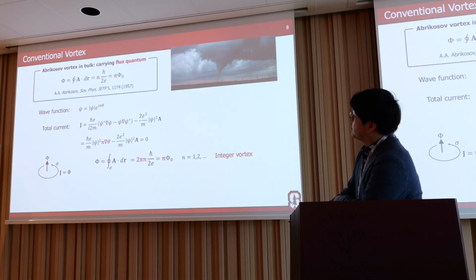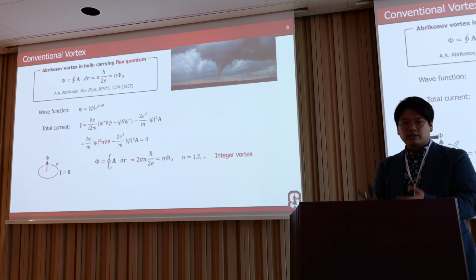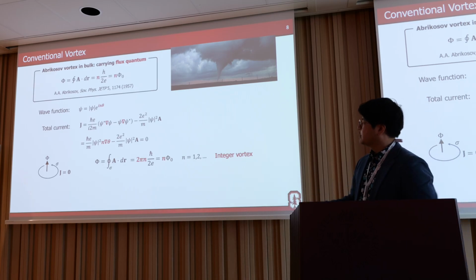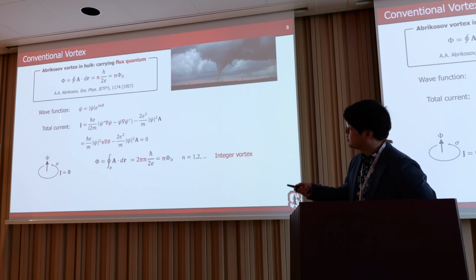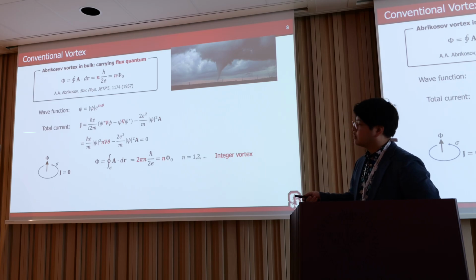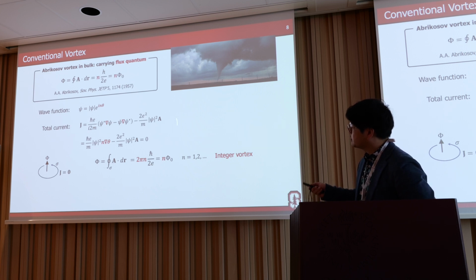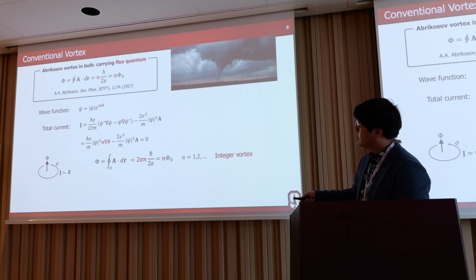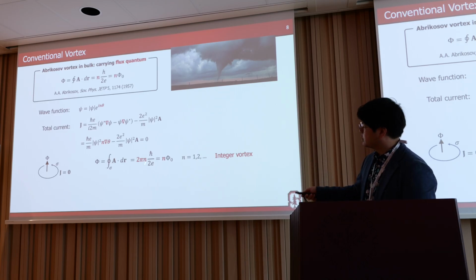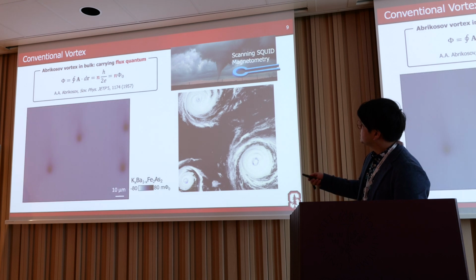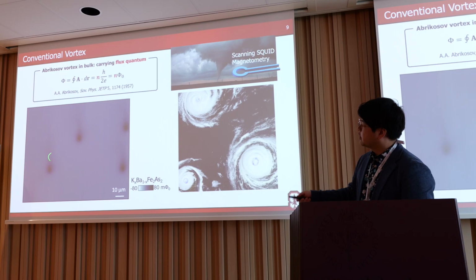Okay, let's first. As you know, in a bulk superconductor, magnetic flux is quantized in each vortex. I think of the wave function with its amplitude and quantum phase, and the total current can be written as two terms: the phase winding term and the vector potential term. The total flux in the vortex is the integral of the vector potential around a path. If the path is far enough from the vortex center, the current term equals 0, and then we only need the phase winding. Because of the quantum condition, this is an integer, so we get the integer quantum vortex. In our measurement, we see this magnetic flux is localized at the vortex center.